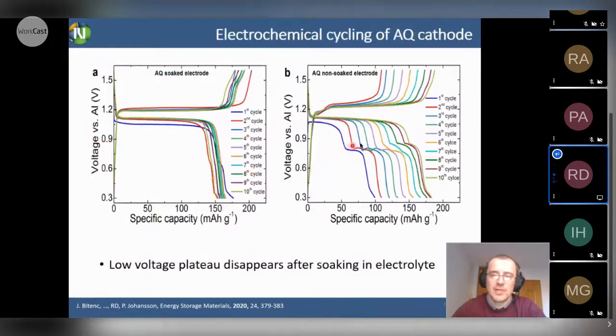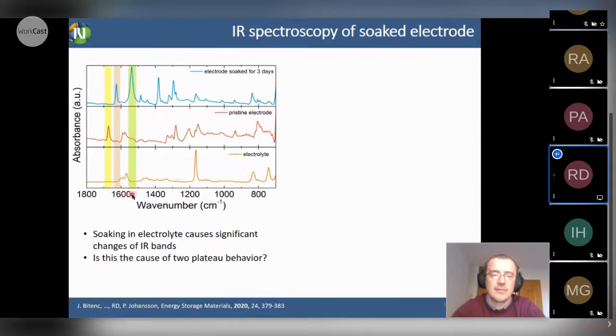And so this lower voltage is from our quinone molecules that are not yet affected by the presence of aluminum chloride, and this upper voltage is from quinone molecules that are affected by the presence of the aluminum. And that was then confirmed also with IR spectroscopy of the soaked electrode compared with the pristine electrode. You can see that we have 2 different positions, for the pristine electrode and for the electrode which was soaked for 3 days. So the IR band for the quinone shifts to lower wave numbers.